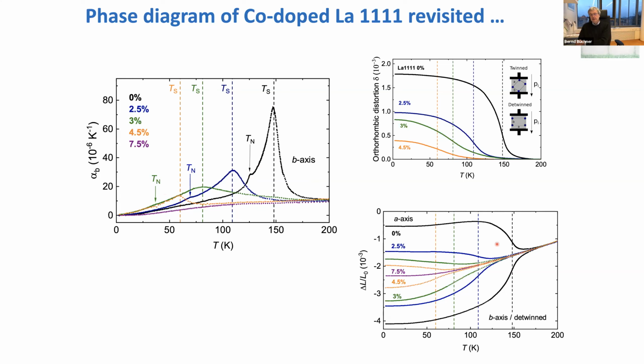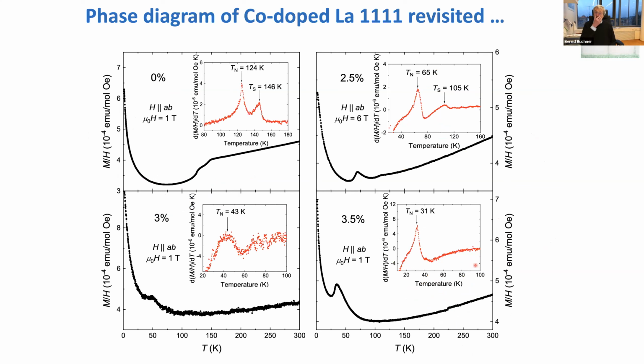And you can also see that from the lattice constants, which you can derive from such kind of measurements by measuring twinned and detwinned directions. And then you see this sharp transition becomes broader and shifts to lower temperatures before it disappears. You can also, of course, measure the magnetization just to follow the phase diagrams. So for the parent compounds, you clearly see these two phase transitions. And if you start to dope, the structure becomes very broad again. Surprisingly, the magnetic transition becomes sharper, very nice visible. Some probably telling us something, but it at least gives you the chance to measure the phase diagram.